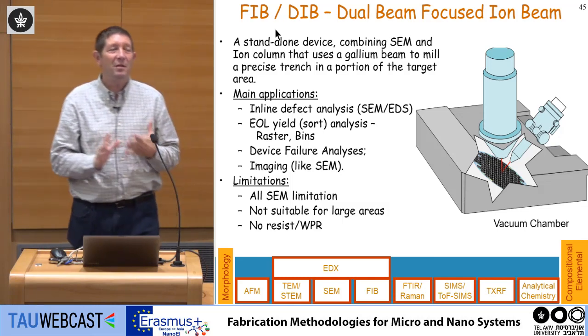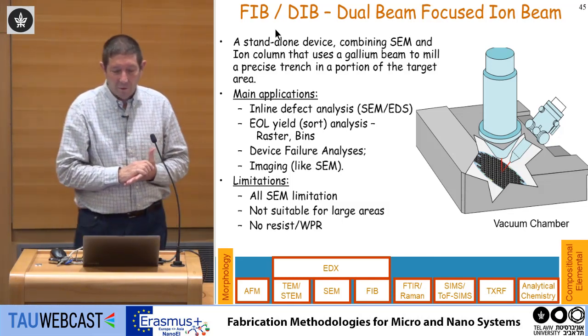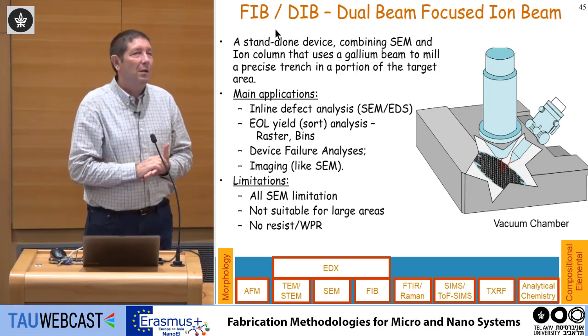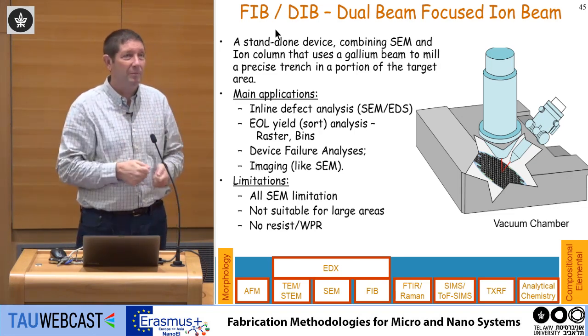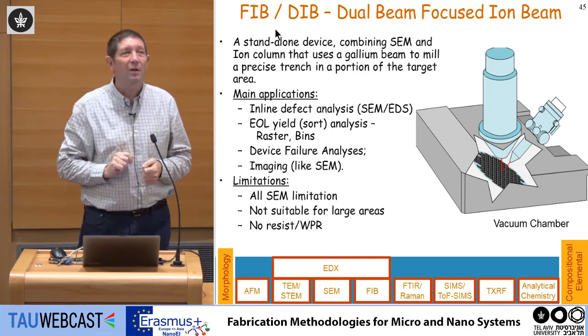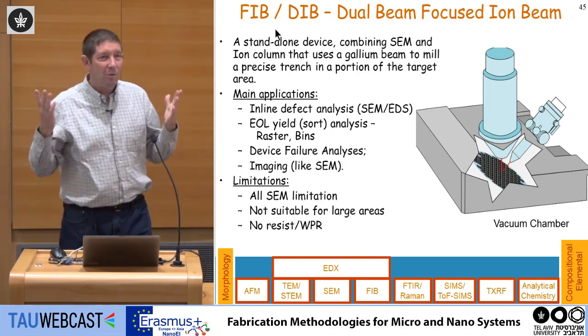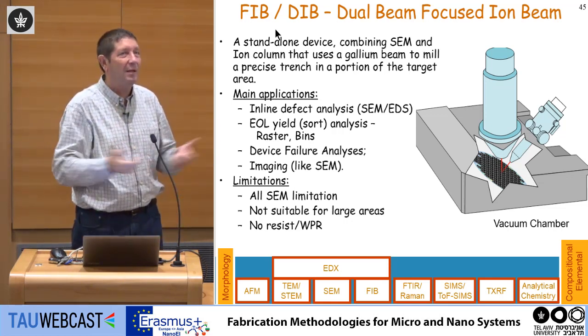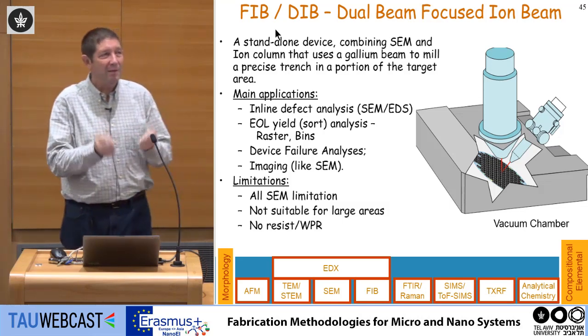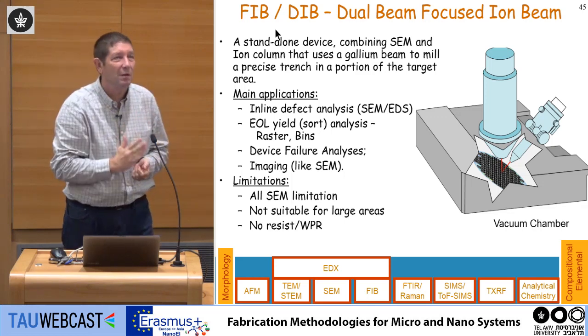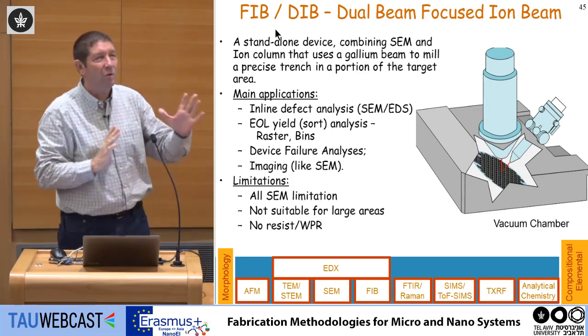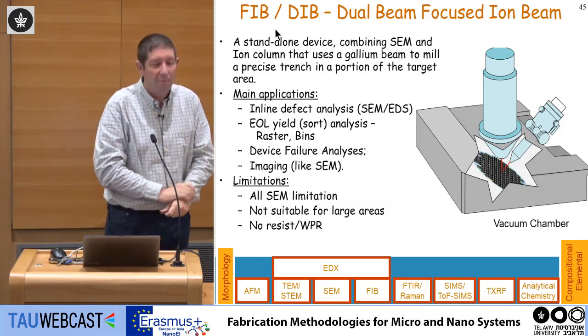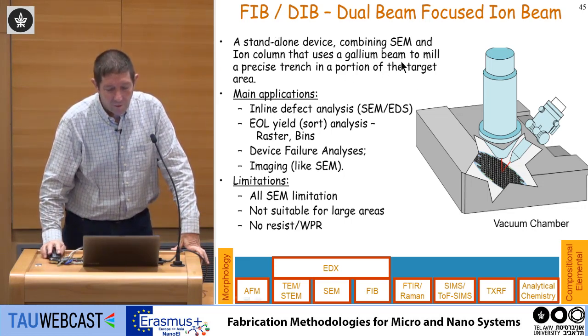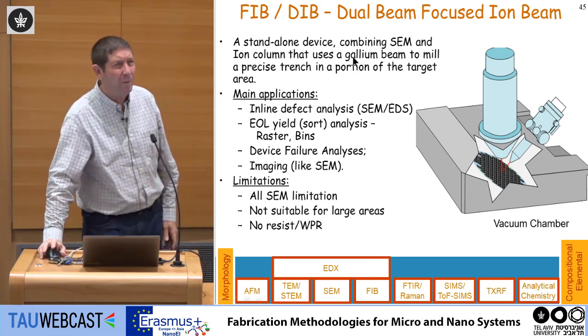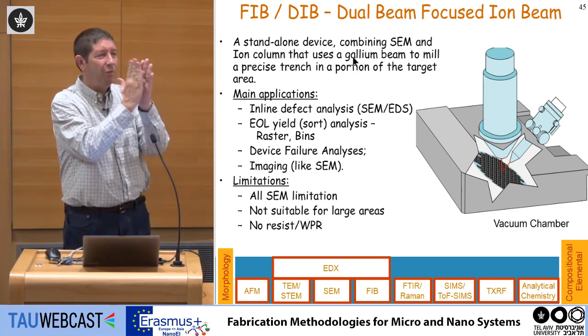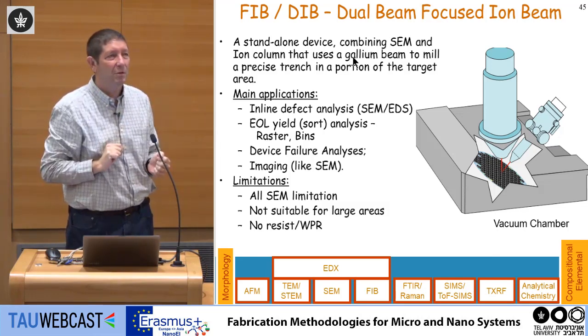And the reason why people built such a system is because there is a big problem to make samples. In the good old days, what we used to do, we took the sample and broke it. Simply cleave it, or try to be very careful, and then you have to polish it a little bit. But it was a completely destructive method, because once you take the wafer and break it, you cannot put it back into the fab. Also, when you break things, not always the surface is nice. Sometimes you have facets, sometimes it's not always going the way you like. So people found a much better way to make samples using an ion beam, which means you can take a gallium beam. Most people use gallium. You take the beam, and the beam is very focused. So you can actually take the beam and cut a trench inside your sample and take a look at it.